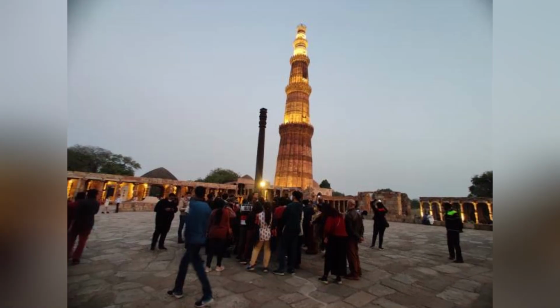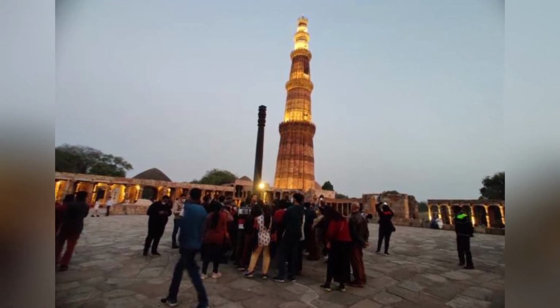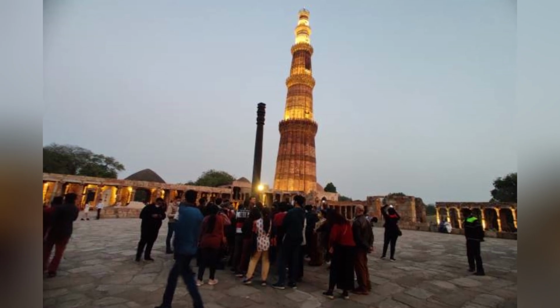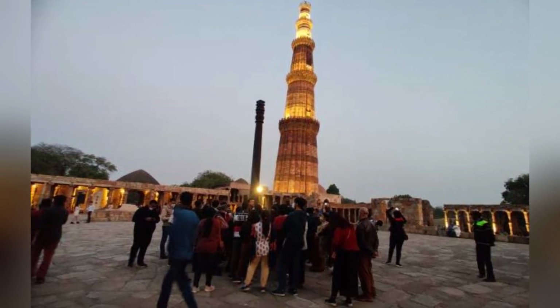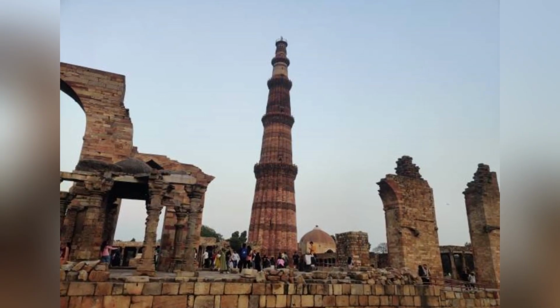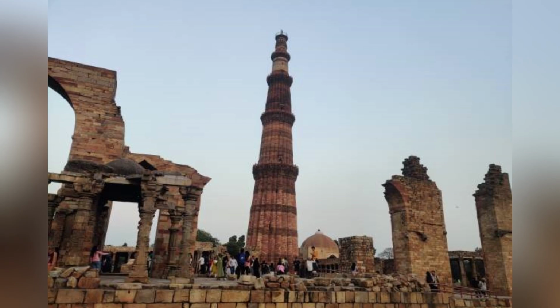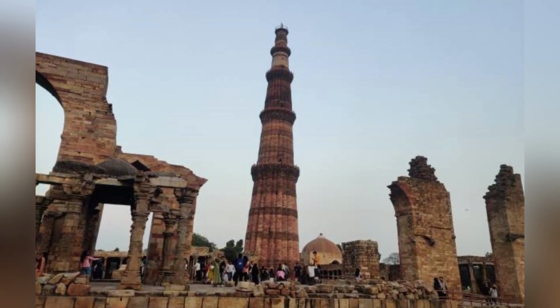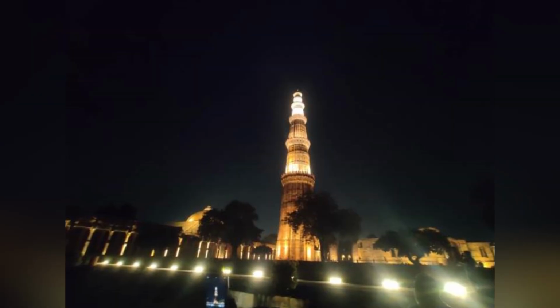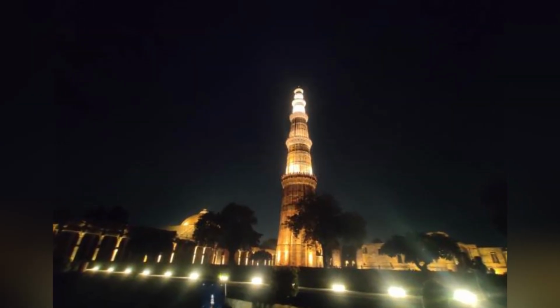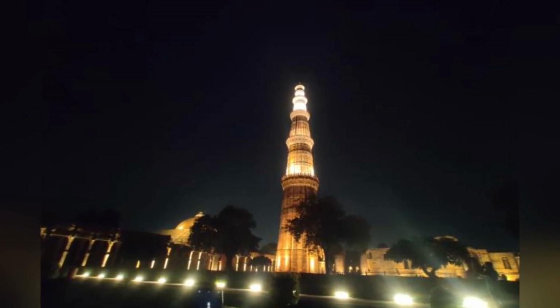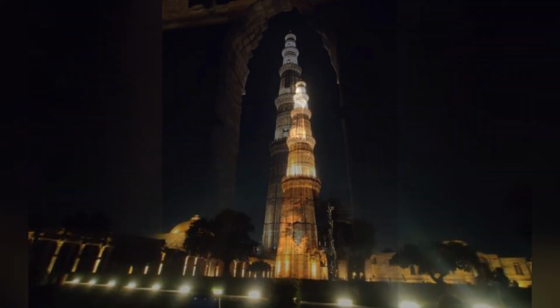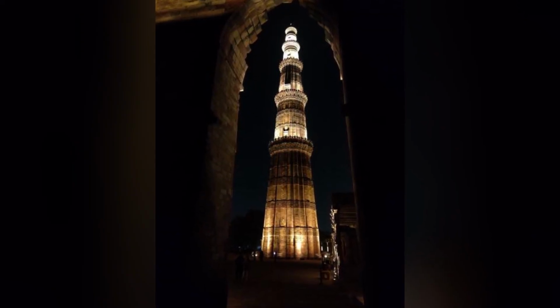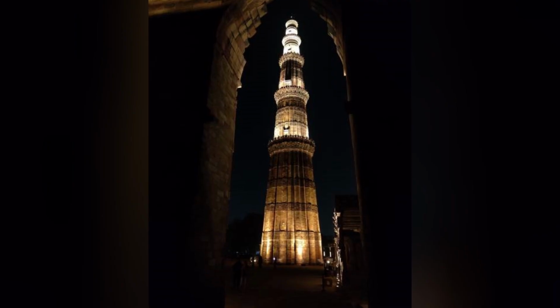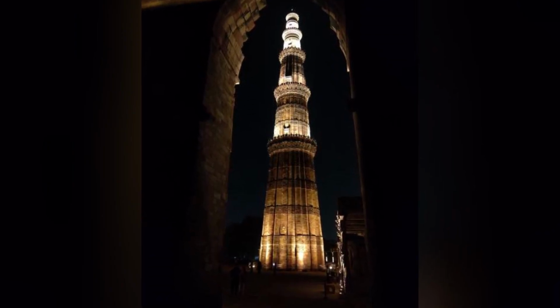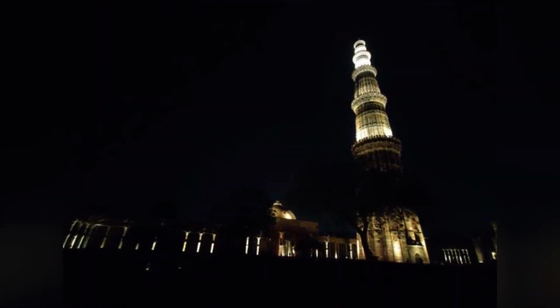The significance of the high phosphorus content for the corrosion resistance of the Delhi pillar was not recognized until the late 20th century, when modern analytical techniques were applied to the study of the pillar's iron and its protective surface film. The traditional explanation, accepted by metallurgists for decades, was that the pillar was made of an unusually pure iron that resisted corrosion because of its low content of impurities such as sulfur and carbon. This explanation, while partly correct, was incomplete, because it did not explain why other ancient iron objects with similarly low impurity contents did corrode, while the Delhi pillar did not.